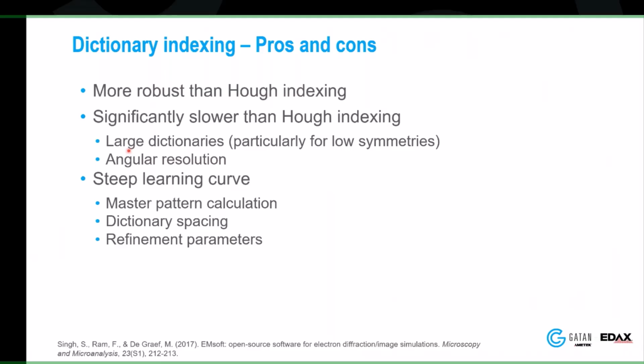And those are completely beat up materials. And dictionary indexing does an incredible job in that material. And that's really kind of the first data set I saw that really said, oh, wow, this is really robust, because the patterns there were just destroyed. There's very little information in the patterns because of how deformed this material was.